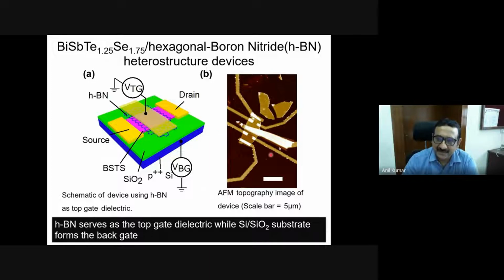Now, if I look at the device here, this is prepared by electron beam lithography, and this scale bar corresponds to 5 micrometers. This is the flake which we are talking about, and this is one electrical contact, and this is another. This is the one used to pass current through it. If you measure the voltage across these two, you get the Hall voltage, and across these two, you get the resistance. And this is the top contact; if I apply a potential through this line, I will be applying the gate. So I can do all sorts of studies in this kind of material.